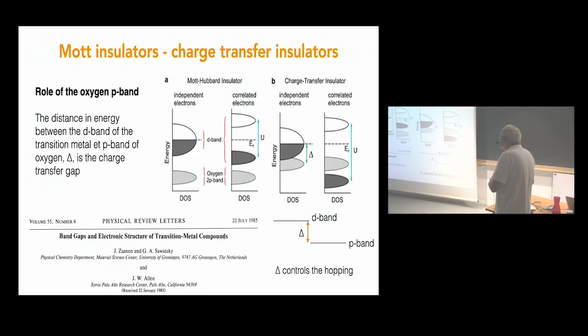And this is the idea which is behind the Mott transistor. One more thing to mention is the difference between Mott insulators and charge transfer insulators. Now this is the role of the oxygen p band. And the distance in energy between the d band of the transition metal and the p band of the oxygen, delta, is called the charge transfer gap.